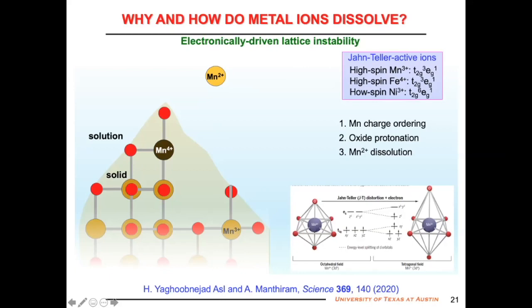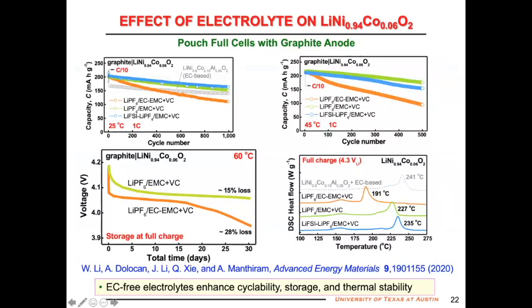So only certain ions which have electronic instability due to one electron in the eg band, that causes dynamic or static lattice instability, lead to manganese dissolution. So far I talked mainly about the cathode stabilization, both bulk and surface, but we have to also work with electrolyte. So for example, I show something here: some electrolyte having EC, this does not have EC, and we also change salt.